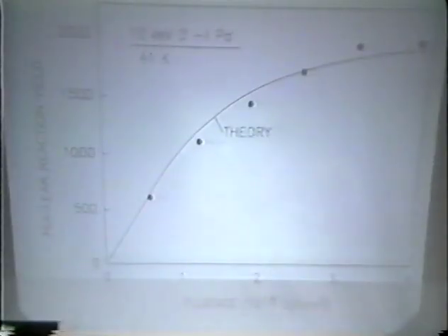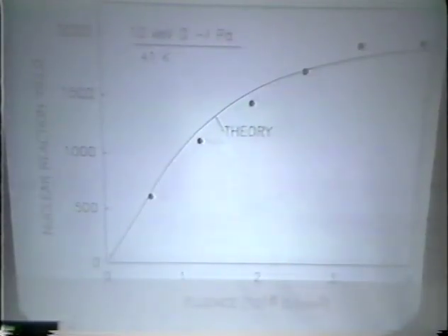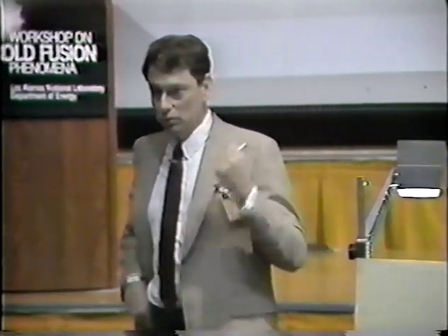Another indication is that we're monitoring this buildup and saturation through the nuclear reaction, and we thereby have information on the concentration. One can, in fact, model this in some detail and thereby establish reasonably well what the concentration is. In the model calculation, the key inputs are the depth distribution of the implanted deuterium, the deposition profile, as it were, and that can be rather reliably calculated using Monte Carlo methods.